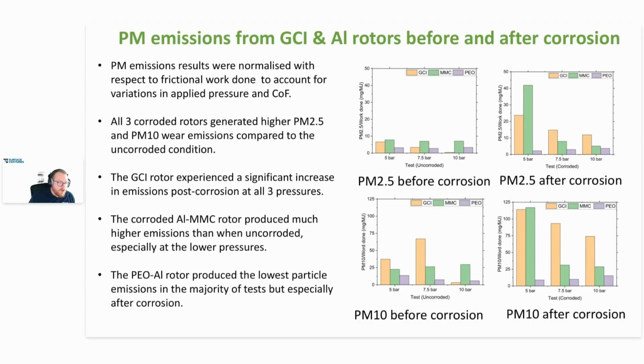Emission from the metal matrix composite rotors also increased significantly after corrosion, especially at lower applied pressures. And in contrast, the emissions from the PEO rotor were consistently the lowest of all three rotors, and importantly, were not significantly affected by the corrosion cycle.